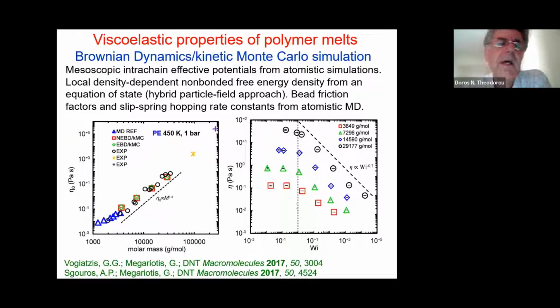So this coarse-grained or mesoscopic simulation from a technical point of view is a Brownian dynamics coupled with kinetic Monte Carlo. Brownian dynamics is so that we can move the beads in three-dimensional space. And kinetic Monte Carlo describes these infrequent events, these hops, and the creation of slip springs at chain ends. Of course, we need an effective energy function, a free energy essentially, with respect to the bead positions and the connectivity of the polymer. And that consists of both intra and intermolecular contributions.